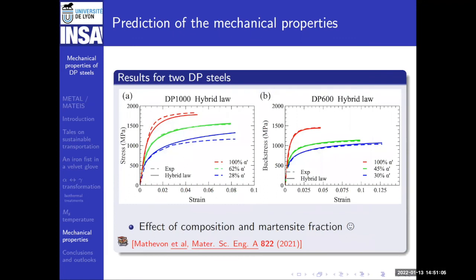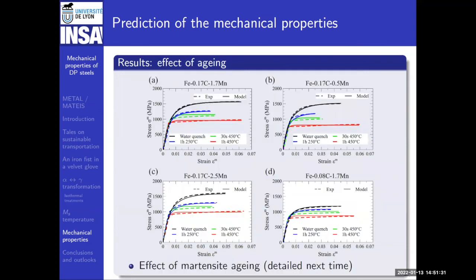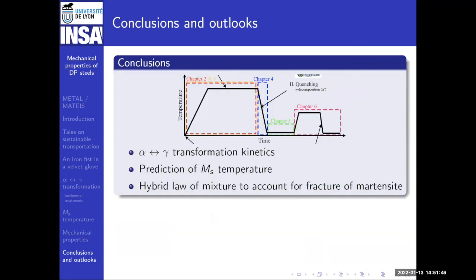What we also checked, but that's another story, is that we could also predict what is happening during aging, modifying the amount of carbon that was in solid solution. You know that if you age a martensite, carbon will precipitate, and if you can predict how much carbon can go in carbide and leave the solid solution, you can predict the mechanical properties of the martensite and of the composites. This is the result of aging at different times and different temperatures, and we can predict quite correctly the evolution of the structure on aging.